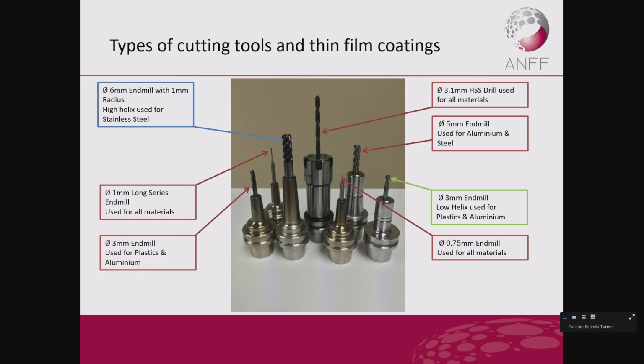And they're even going to ceramic coatings now, where the tool doesn't even work properly until it gets up to 900 degrees. So some of these coatings allow us to keep the tool sharper for longer, and it's not affected by the build-up of heat. You'll also see that the geometry on the tip's slightly rounded, because if we had sharp geometry and we were trying to cut stainless steel, it would just chip instantly. So we've increased the strength of the tool by putting a radius on there.